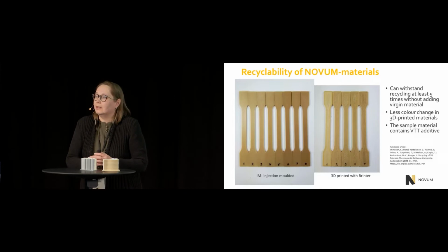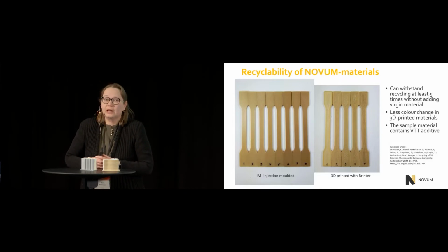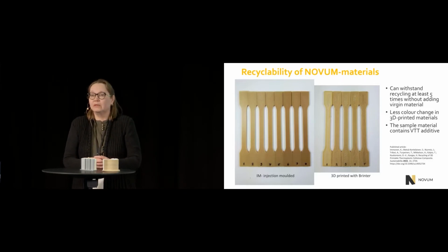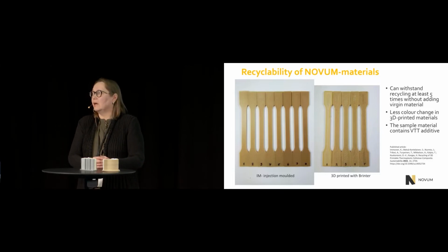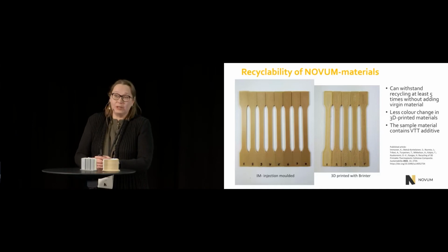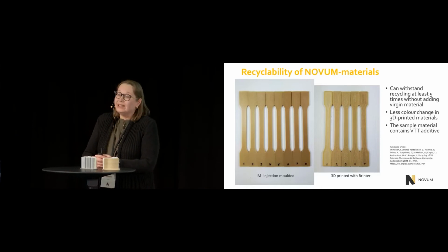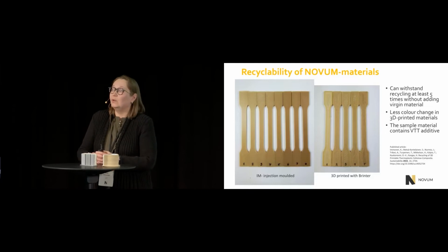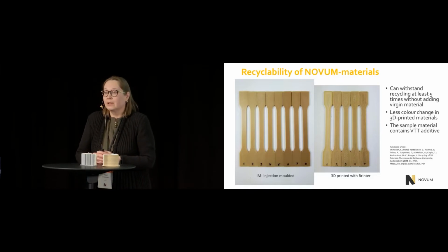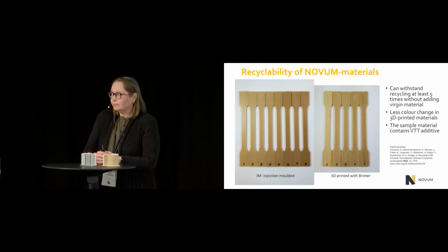And then recyclability of this material was also mentioned, which is a very, very important issue from the material tailoring point of view. And we have studied the recyclability of these new materials and found out that it can actually withstand 5 recycling rounds without adding any virgin material.